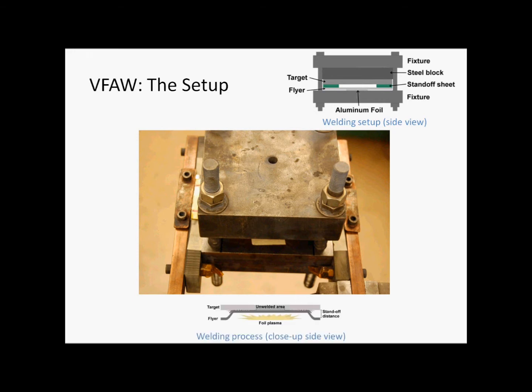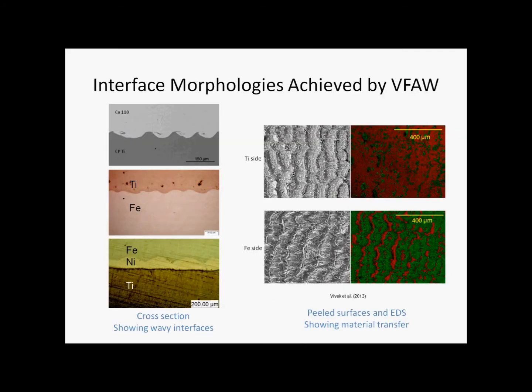Below is a side view of the welding process. The rapid vaporization of the foil propels the flyer toward the target into a high-speed collision, resulting in a welded joint. A material joint made by VFAW exhibits the wavy interface which is characteristic of collision welding. It is similar to that which is observed in an explosion welded joint, but on a much smaller scale.